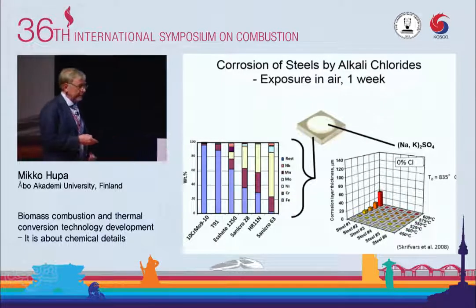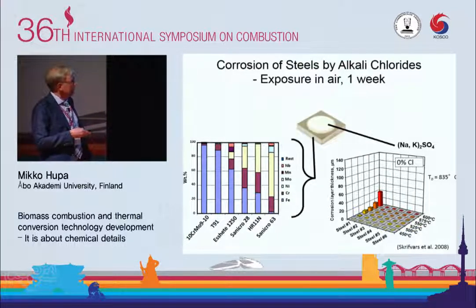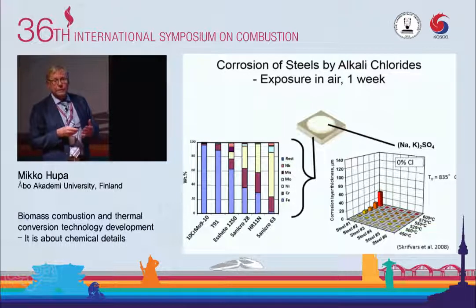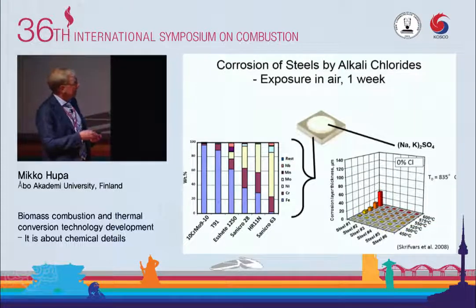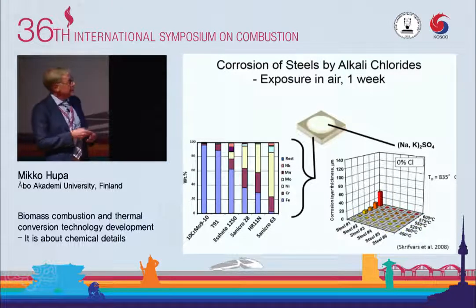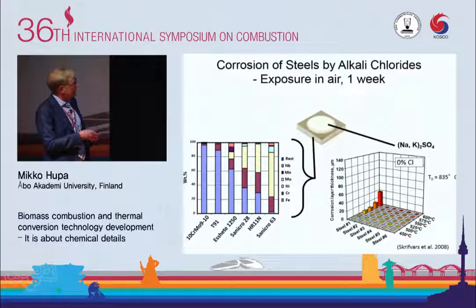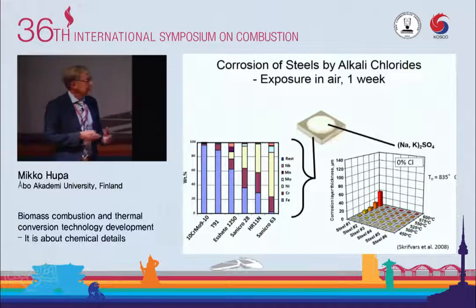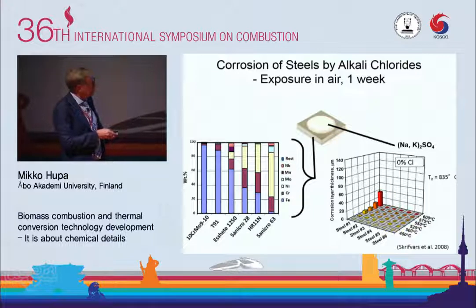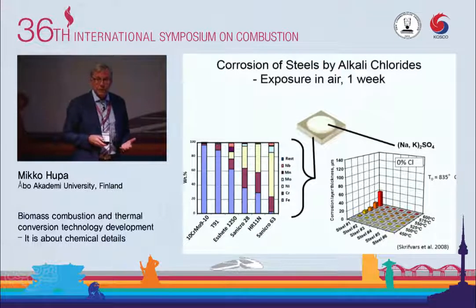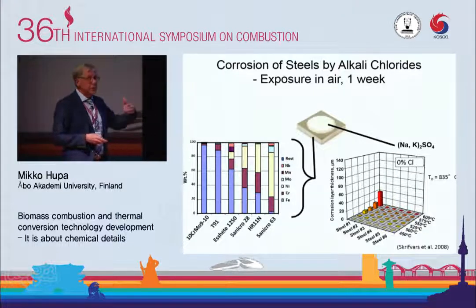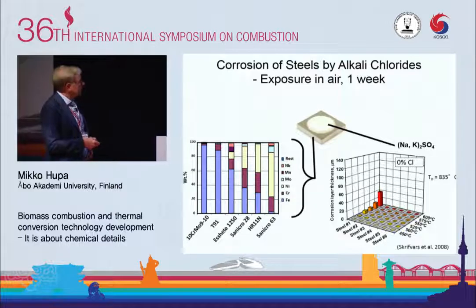Now, then we did a full series of temperatures 450 to 600 with all these steels. And in fact, our students did all these tests, but under these conditions, when we used only as base material alkali sulfate, no chloride yet, we got no corrosion for most of the steels except the steel number 1, which is the low quality. And this is not caused by the salt. This is just any oxidation of that material at high temperatures. But you could see that if we have no chlorides, we could easily have material temperatures up to 600 with all these materials without any problems. That would be very welcome because then we would be able to go higher temperatures, steam temperatures.